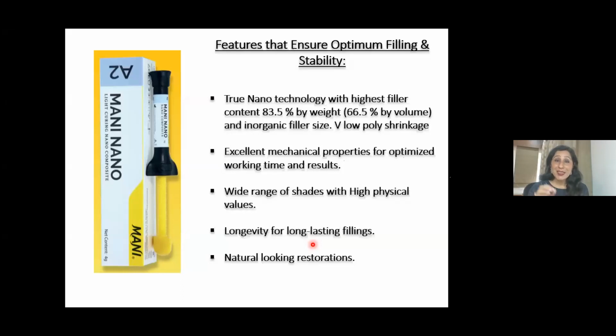What I want to emphasize now is it has such a great amount of filler, the highest filler content of all the composites, and that is 83.5% by weight, which is really a very good filler content. Jitna zyada filler content hoga, polymerization shrinkage will decrease. So the polymerization shrinkage is therefore very less for them. They have a very good longevity for restorations, and they can produce natural looking restorations as well.